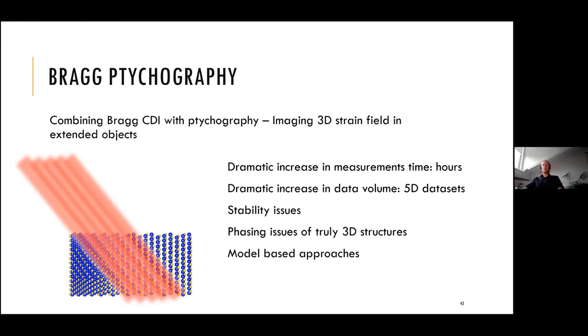The dramatic increase in the data volumes. It's five-dimensional data sets, which can get to gigabytes and gigabytes in size. The stability issues start to play a major role because of the measurement times, and then phasing of actual three-dimensional objects can be challenging since you have to impose certain constraints and it's not very easy to do. Or you use model-based approaches to explain what actually is reconstructed in your experiment.